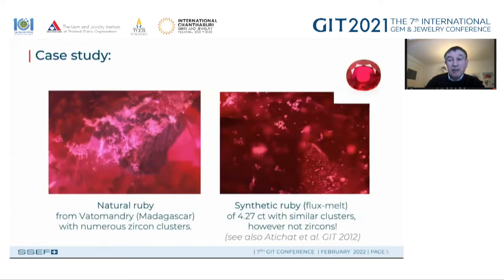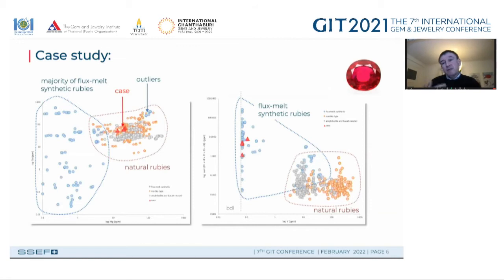I just want to show you a case study, I would say actually rather a classic. What you see here are two microscopic images. You see on the left side a natural ruby from Madagascar, from Vatomandry, showing these clusters of zircons. And on the right side, you have a situation of a flux melt synthetic stone, where you have similar looking clusters, which are, however, no zircons. So looking at this, it seems to be quite the same. And for sure, this synthetic stone comes along with papers telling that this stone is a natural stone, which is not the case. So we have to look into trace elements.